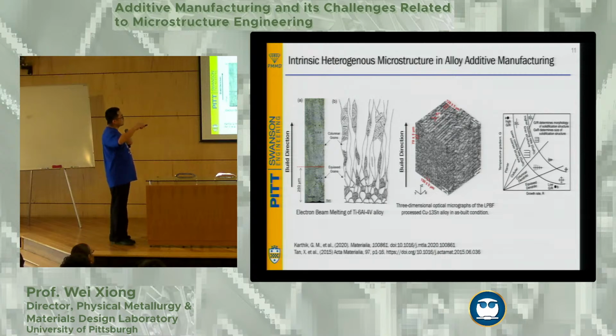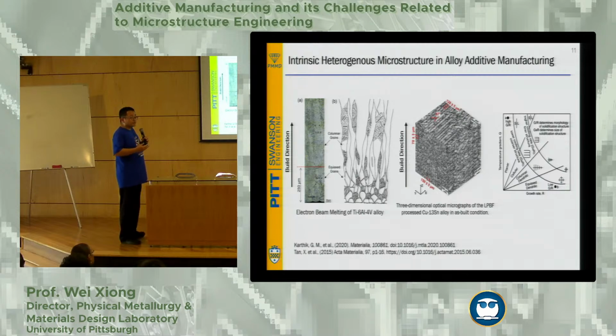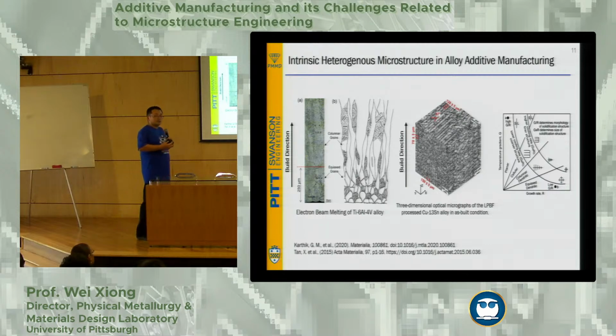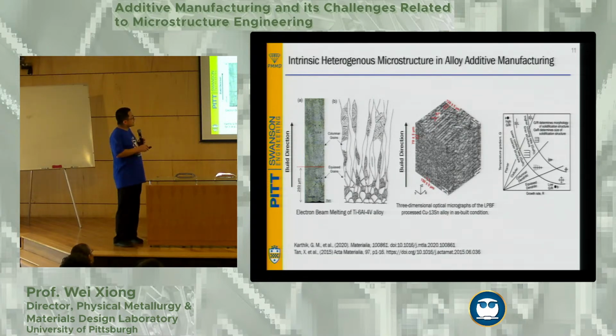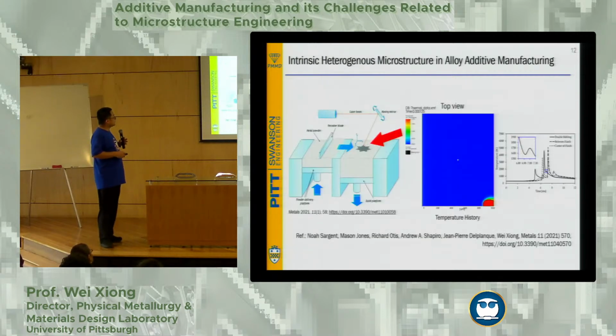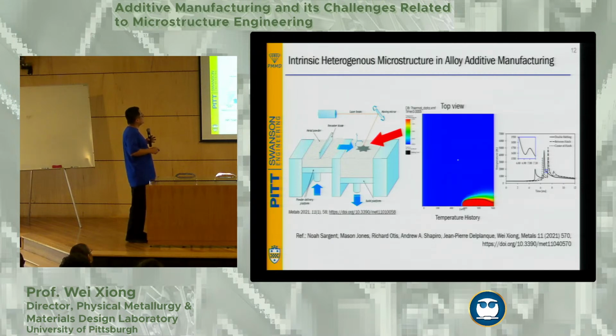However, if you look at another transverse plane, you probably don't see all of these melt pools. And of course, this also brings us another design area where you can change and modify all of these printing parameters to control the growth of the material from the initial point. And therefore, you can actually tailor some structure with the columnar, tailor some structure with the equiaxed. Then you can start talking about heterogeneous grain. Okay, so that's one of the things we can look at, some opportunities there.